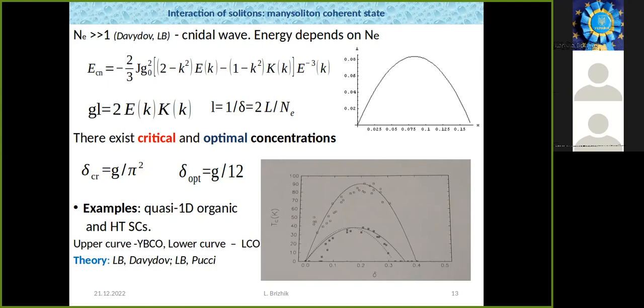This theory we have applied to explain the dependence of the critical temperature of superconductors, for instance, of the high temperature superconductors, on the concentration of charge carriers, on doping. And in the lower figure, we can see critical temperature as a function of concentration. Lines correspond to our theoretical model. Points, symbols correspond to experimental data. The upper curve is for yttrium systems and the lower is for lanthanum compounds. The next slide, please.